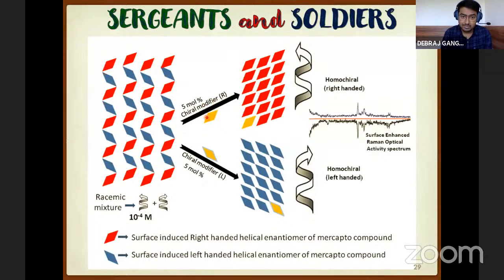So the right-handed chiral modifier will align all the molecules present within the racemic mixture towards the right-handed orientation, and the left-handed modifier will align all the molecules, all the left as well as right-handed molecules in the racemic mixture, in the left-handed orientation, and we may get a surface-enhanced Raman optical activity spectrum.